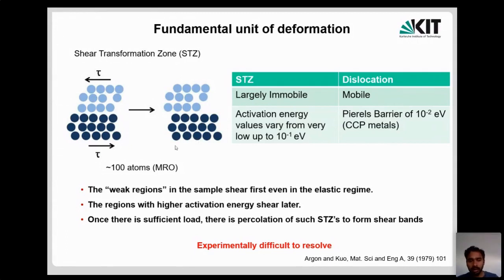And this is in the range of 100 atoms, so you are dealing with something like 1 to 2 nanometers, in the medium range order zone. However, in this medium range order, like I told you, we have the short range order clusters. And the short range order clusters can have different kinds of coordination. So some are loosely packed, some are densely packed. The loosely packed clusters would be the ones which deform more quickly. That's the one point I want to highlight from this slide.